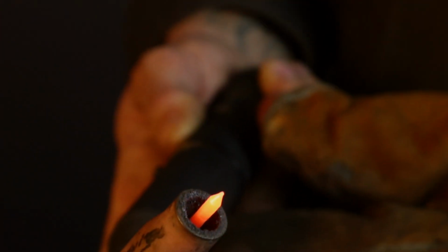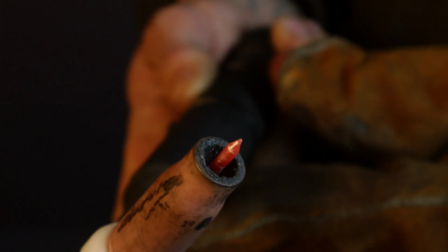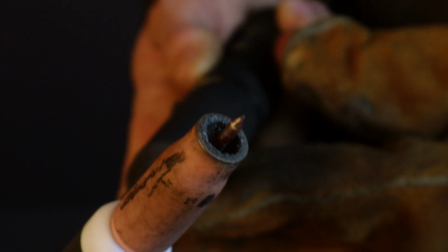After all, in the first seconds after welding is stopped, the tungsten electrode maintains a high temperature and starts to burn when oxygen enters. This does not happen in a protective environment, but it is possible when oxygen enters. In this case, the structure of tungsten is damaged and it will be unsuitable for the next welding.